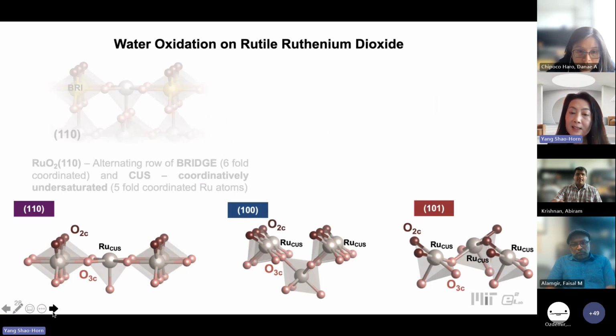We can also study different surfaces, right? And ask the question: are, let's say, all the CUS sites the same? So for example, if you have 110, 100, and 101, you can see the CUS site is MO5. They're all very similar from the first coordination, but in the second coordination, they are different, right? So we can also ask, using both combined DFT and synchrotron measurements, can the CUS sites be different, and how might the CUS sites be different if they exhibit different activity?